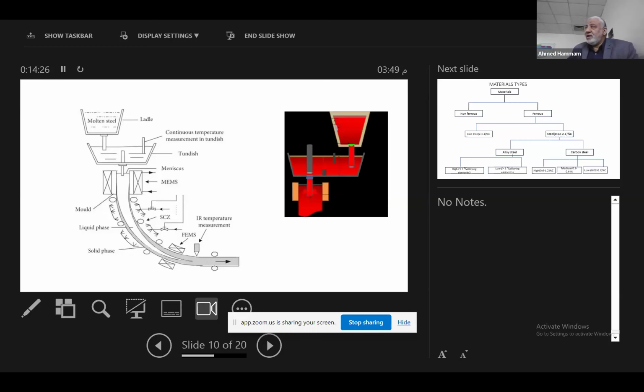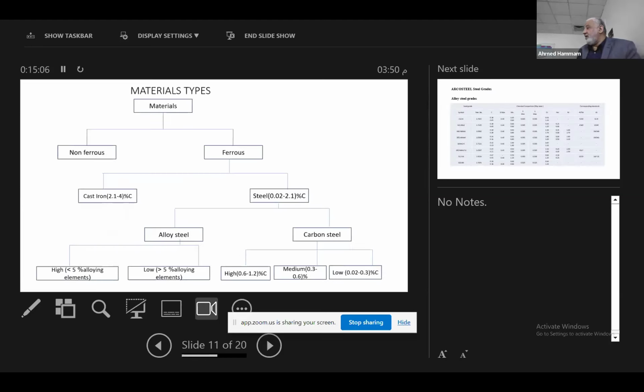After that, we go to the continuous casting machine, which starts with the molten steel in the ladle. There should be a shroud between the ladle and the tundish, and also another shroud up to the mold. So it's a closed casting procedure. By this, we can control and ensure that the final results will be in good condition, followed by primary and secondary stirring in the mold to keep homogeneity for the final product.